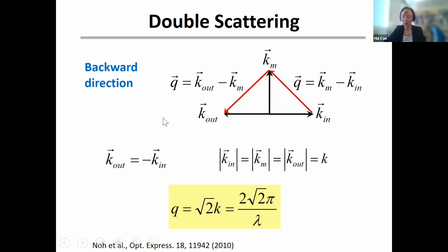Let's consider the backward direction here. Now we know all these K vectors should have the same magnitude because we consider elastic scattering. And from simple math, we can see that again the dominant spatial frequency Q will determine the wavelength for double scattering, and this wavelength is different from single scattering. That's why we see a secondary peak or shoulder in this optical reflection spectrum that comes from double scattering. But again, this scattering is coming from the dominant spatial frequency, or the periodicity, in the structure.